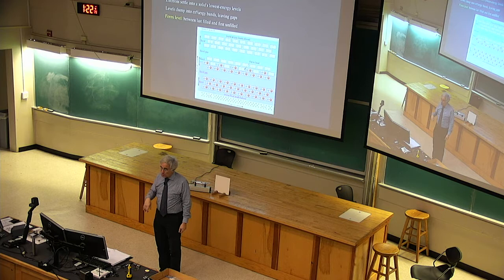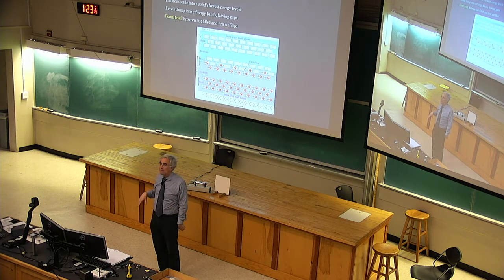So we're turning to this. If you've got a solid where you filled all the levels in the bands with electrons, and you try to get those electrons to rearrange, they can't do it. Not without a big investment of energy. Why? Because all the levels with similar energies are full, and the Pauli exclusion principle forbids you from piling extras in.